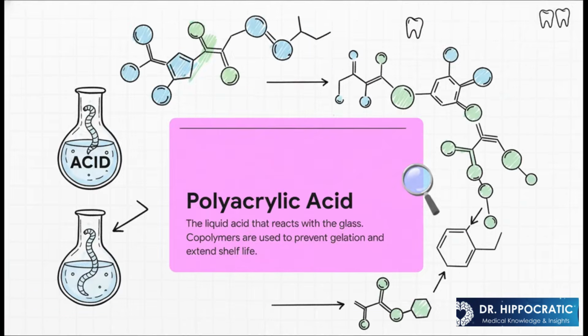The liquid part is an acid, usually polyacrylic acid. Now, the early versions had a major problem. This liquid would thicken up and turn into a useless gel over time. The fix was a fantastic bit of chemistry. By using copolymers instead of homopolymers, they completely stopped the gelling. This wasn't just a small fix, it was a total game changer that gave the material a long shelf life and made it a reliable tool for dentists everywhere.